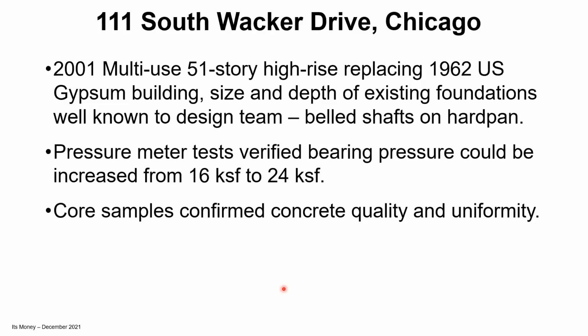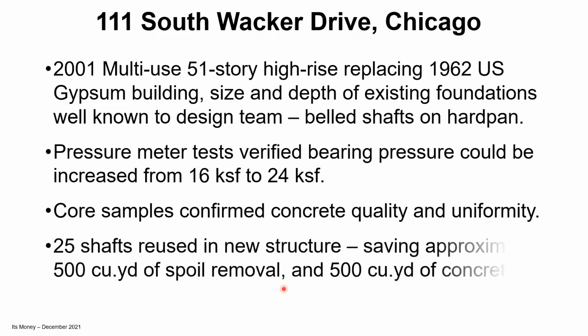Core samples were taken from several of the existing shafts to confirm concrete quality and uniformity. And in total, 25 shafts were reused in the main structure. The shafts were various sizes. The existing ones ranged from 2.5 feet to 5 feet in diameter, and depths were around 40 to 50 feet.